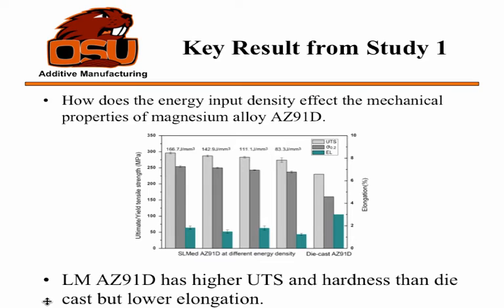And this is one of the important things that I was able to take away, is that a fairly high specific energy on SLM parts produced the best UTS and strength at 0.2%, which I guess that's yield, and then elongation. So, and that's compared to traditionally die-cast AZ91.